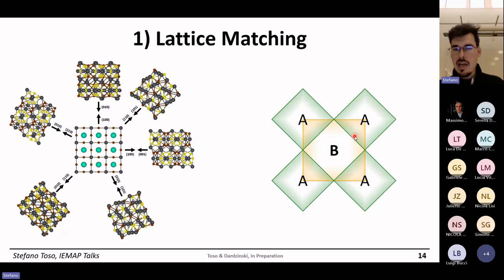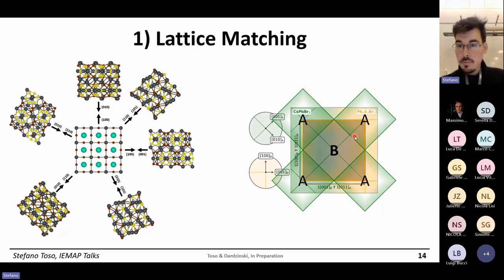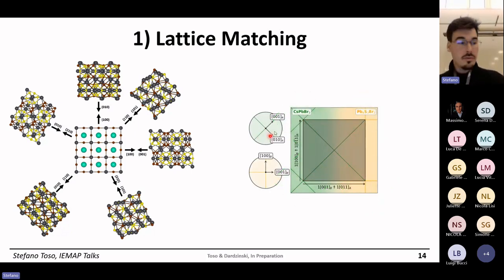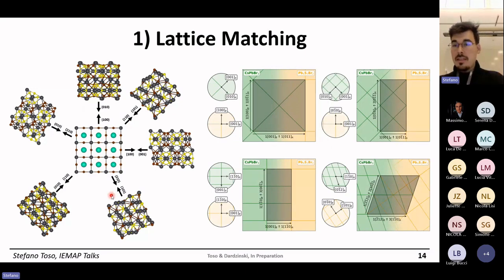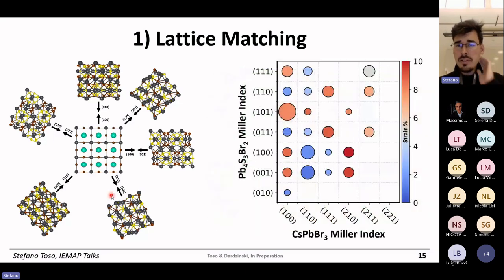Now, this situation is automatically identified by our code, actually. And it is described with this kind of tables where you see the 2D lattice of one material, the 2D lattice of the second material, and the supercell. You can have, of course, many, but this would be difficult to read for a user, right? So what we do is extract the relevant information from these schematics, which are the strain and the supercell area, and we condense them into a matrix that is easy to see. So given one direction for the base material, you can read how well the other material will match on that direction with its own facet.